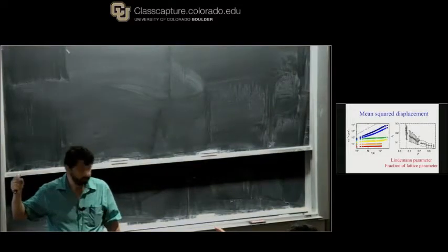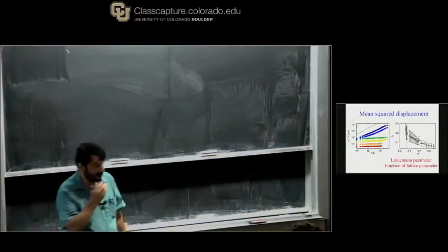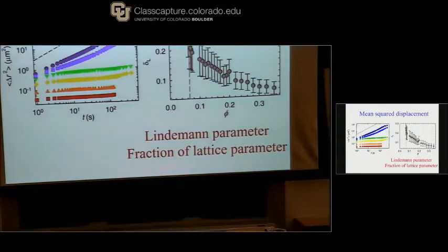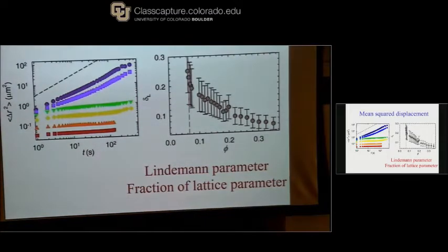So what's on the x-axis, the volume fraction? Yes, this is a volume fraction. Yes, because these are repulsive particles, so they're not hard spheres, right? So they want to repel one another. You're just squeezing them down, even though they're repulsive. So the volume fraction is not the same as the crystallization fraction. Okay, and this depends on the charge. Does that make this then a superheated solid? Exactly right. This makes it a superheated solid.